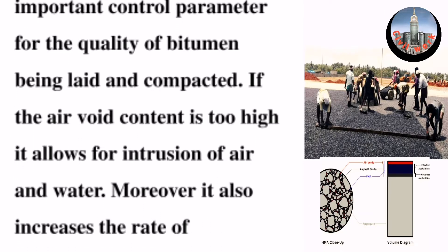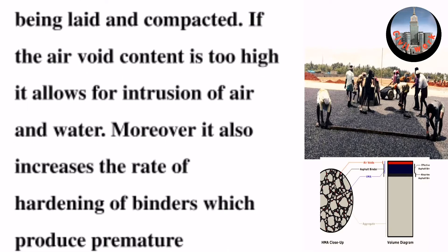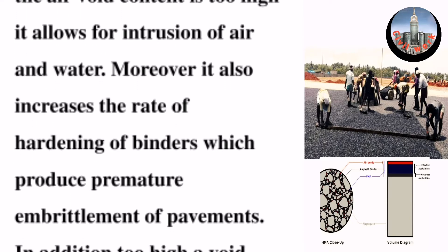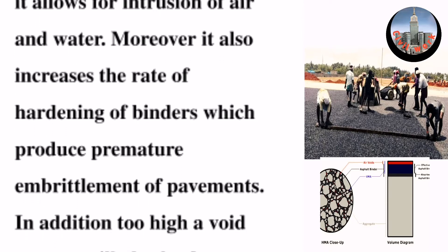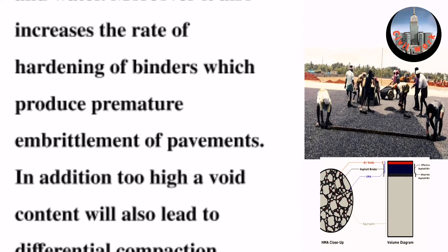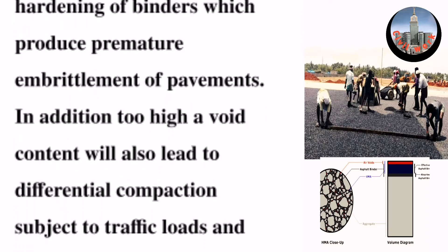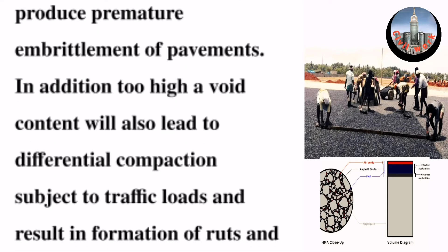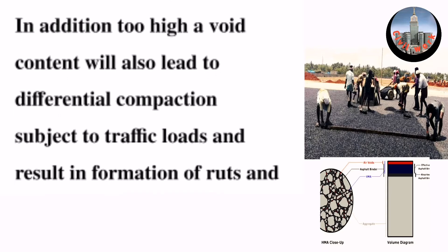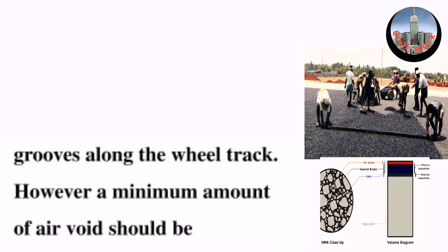If the air void content is too high, it allows for intrusion of air and water. Moreover, it also increases the rate of hardening of binders, which produces premature embrittlement of pavements. In addition, too high a void content will also lead to differential compaction subject to traffic loads.